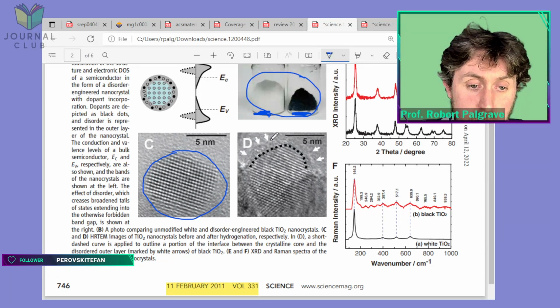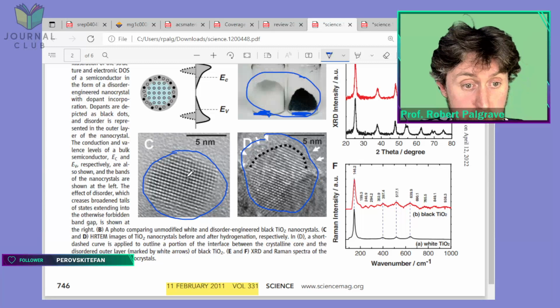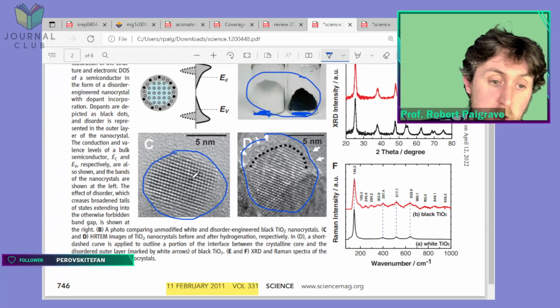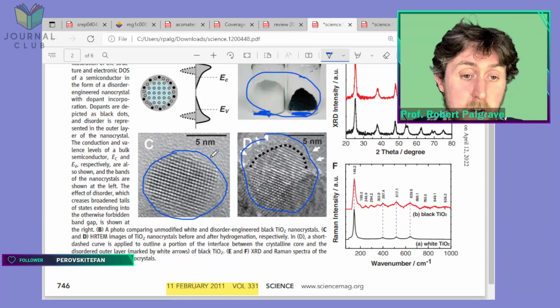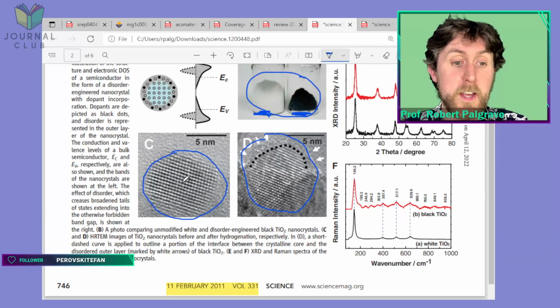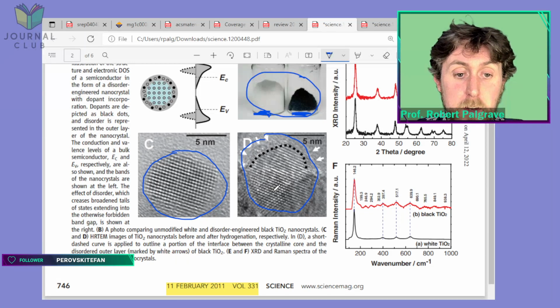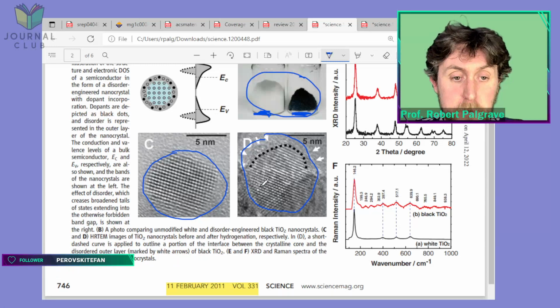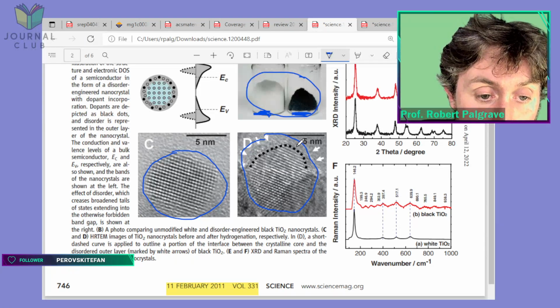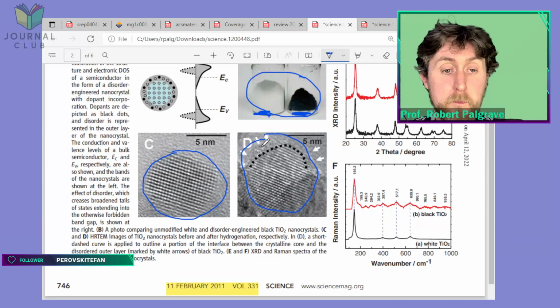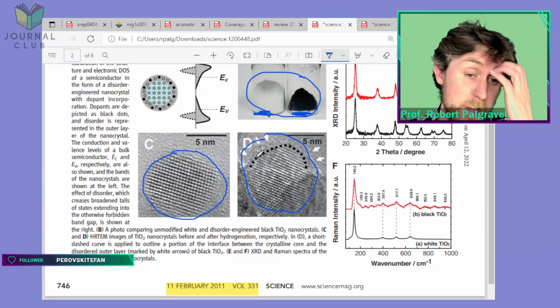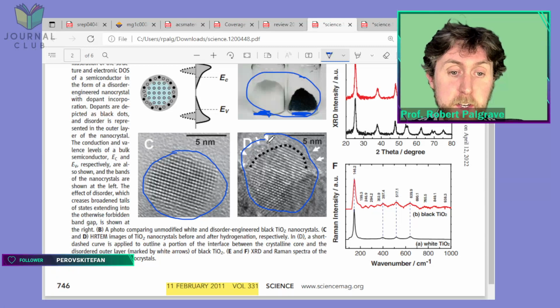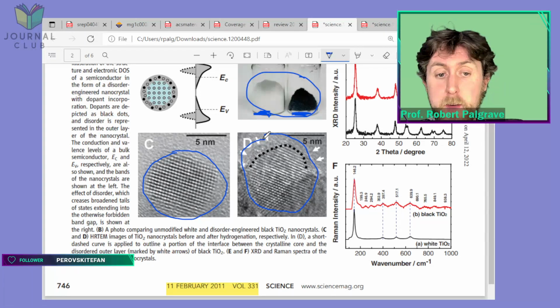But you can see afterwards, and this is what they claim here, after the hydrogenation, you still have this kind of core. The middle of the particle still has this very regular structure. I should say the reason these dots are all lined up in an order is because this material is crystalline. So it's a highly crystalline material, and you can see the arrangement of atoms is very orderly there. And indeed, in the middle of this particle after hydrogenation, you also have an orderly arrangement of atoms. So you still have a crystalline center, but around the outside, this is their claim here, you have part of the particle which is not ordered. So the atoms aren't forming a very regimented, regular structure here. They're much more disordered. They're more randomly arranged.